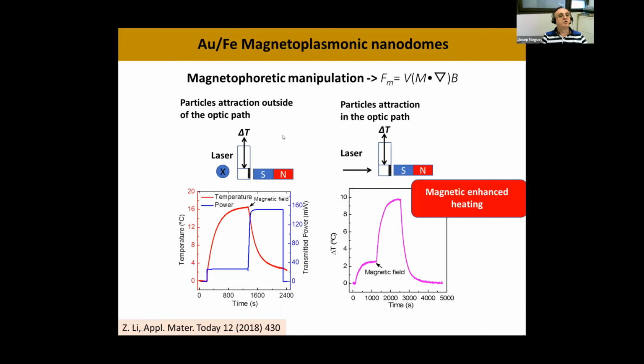So as I show you, the iron layer allows us for easy manipulation. That's done using what's called a magnetophoretic effect, where when we put the magnetic field, the particles tend to go towards the magnetic field. So here I show you how we can control the heating using the magnetic field.